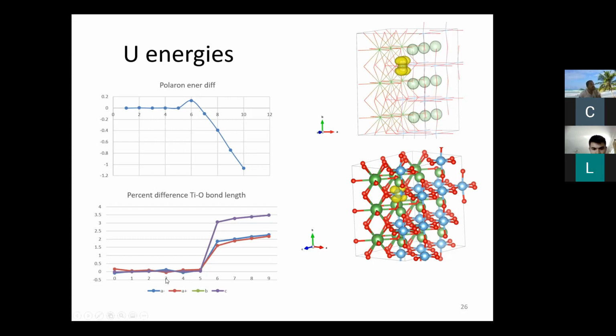One interesting signature that you can use to tell whether you got a polaron, if you didn't have these charge density differences, is seeing a percent difference in the bond length of your site compared to the delocalized case. You can see here that there's a big jump in the bond distances. You could actually see this using spectroscopy too, like XPS and a few different methods. It's very sensitive to the geometry of your system, and you can tell experimentally if you have this.